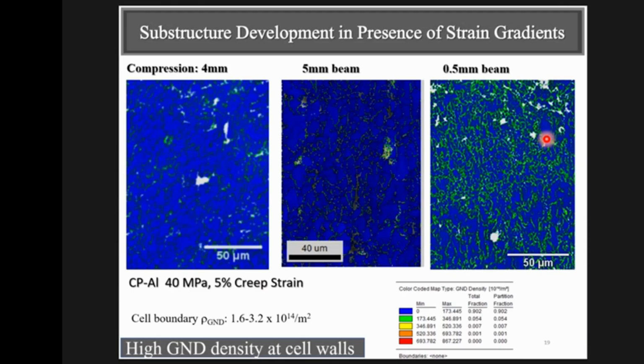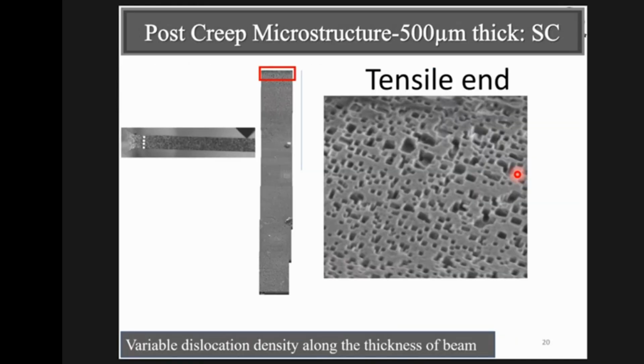Now, it turns out that the substructure that you develop during creep under bending is similar to what you have under uniaxial conditions. So that was established independently. But then when you get to very small beams, you get a much finer substructure of dislocations. And we argued that this is because of geometrically necessary dislocations, because now your strain gradients are extremely high. Remember that at the neutral axis, the strain is 0, and you have the maximum strain at the surfaces. And so these pump in additional dislocations, which refine your structure and thereby reduce the creep rate.